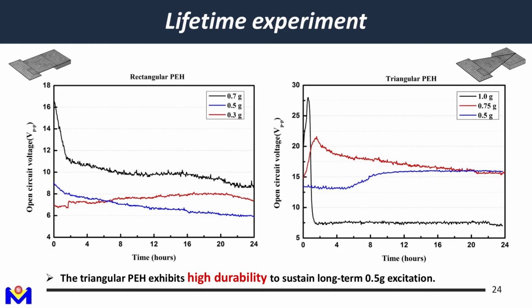But for even larger acceleration, for example, here is 1 G, you can see it fails and drops to very low output within 1 hour. But for rectangular, it's not. And the reason is also quite simple, because the overall stiffness for the triangular one is smaller. So overall, the mechanical strength is also worse compared with the rectangular one. So again, it has to be designed and optimized based on your real requirements on the application side.